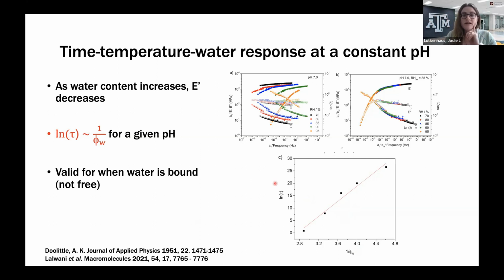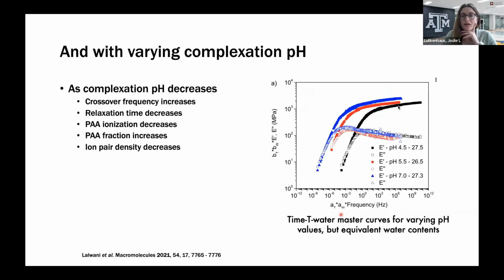This was done only at a single pH though, pH 7. Will this hold up if I change pH? So here's an example where we also explored pH 4.5, pH 7. We did time, temperature, water superpositioning to get these nice curves. We see the crossover frequency is increasing as pH decreases. That relates to a decrease in the relaxation time. Ionization of the polyacrylic acid is, of course, changing, but we can characterize that with FTIR to complete our intrinsic ion pair calculation.